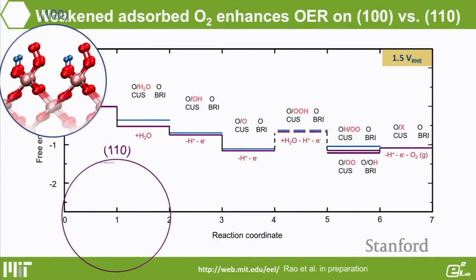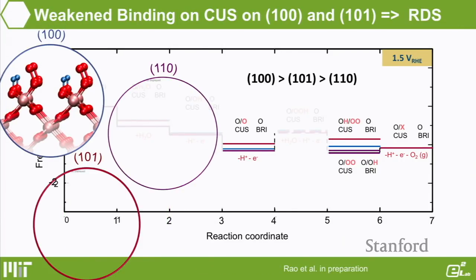So then one would argue, what if I change to different surfaces? So there's something wrong with the graphics. There should be something here for the 110. If you change to the 100 surface, you no longer have a Cus and bridge site; every site is a Cus site. And we see that the energetics of these reaction intermediates change. Particularly for the 100 surface, you can see that it no longer has a barrier for the oxygen evolution step. And if you change further to a 101 surface, you can also change the energetics so that the last step becomes downhill, but the formation of OOH from O becomes rate-limiting. So you can change different surfaces and change the rate-limiting step.